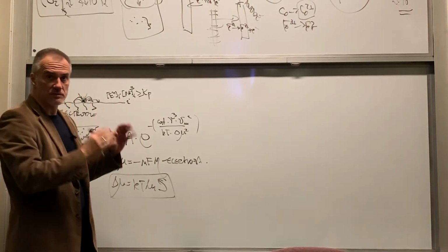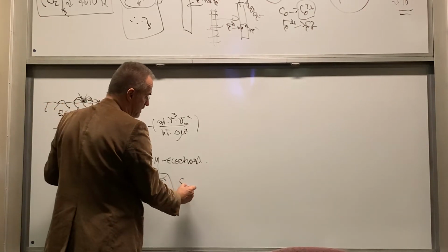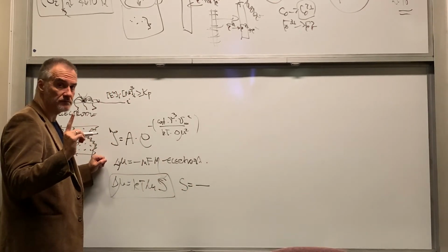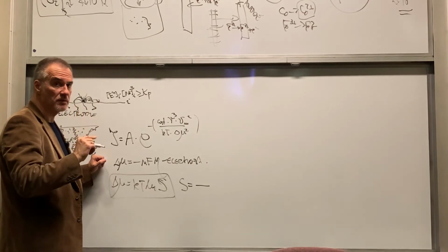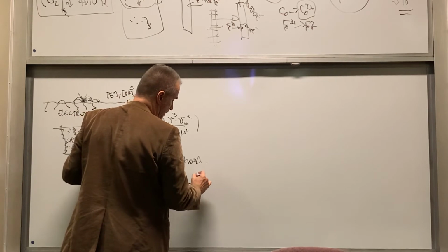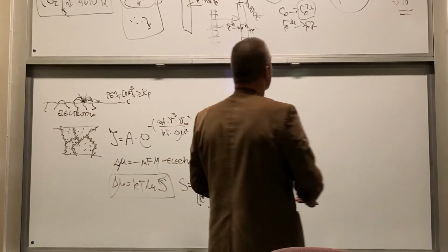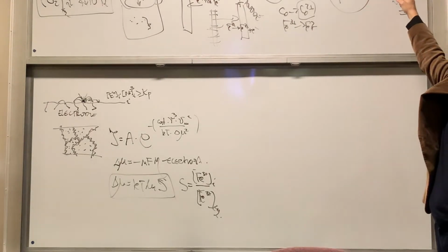In terms of our discussion, I'm going to simplify it a little bit, but the S term here is actually the ratio, and I'm going to focus only on iron concentration for the moment, although you could be more elaborate, between the Fe3+ concentration at the interface and the Fe3+ concentration at equilibrium, which is the one that you can calculate for the known concentration of OH- from the solubility product, right?